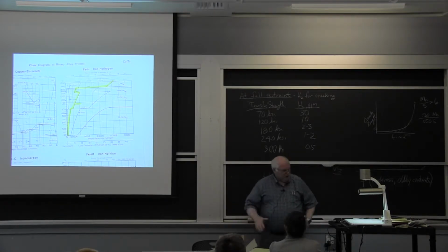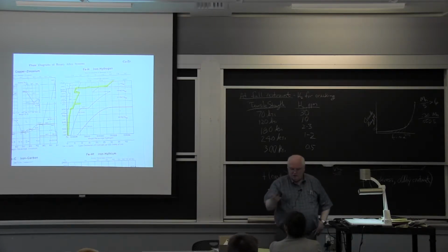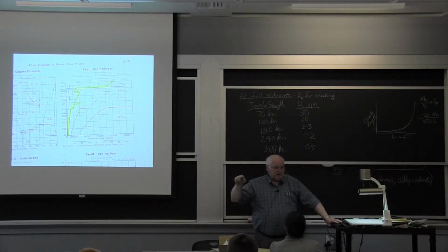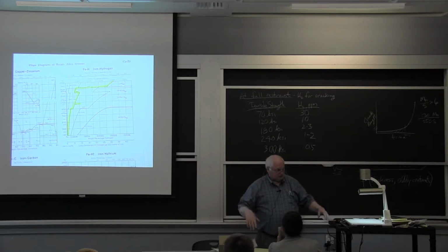You heat them. If you went back to Stout and Doty, that other thing I handed out said stress relief, and it said for A27 steel, desirable 1100 to 1250 degrees Fahrenheit. You put it in a furnace at 1100 to 1250 degrees Fahrenheit for about 1 hour per inch of thickness, so it heats all the way through, and that softens the steel, and the residual stresses will be relieved.